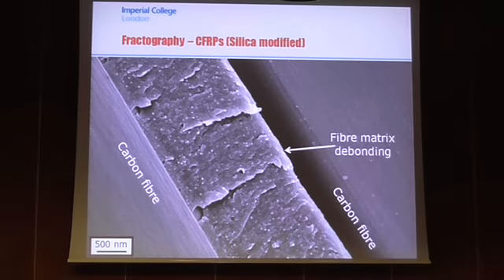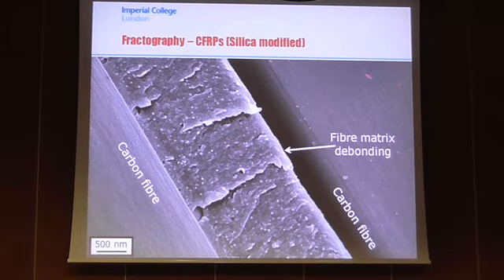So we take a quick look at the fractography. We can see that we have carbon fibres, and these carbon fibres are relatively clean. So this indicates that there's pretty poor adhesion between the matrix and the actual carbon fibres. So we see some fibre matrix debonding, and then we possibly see some debonding of the silica, but we're not 100% sure in that case.